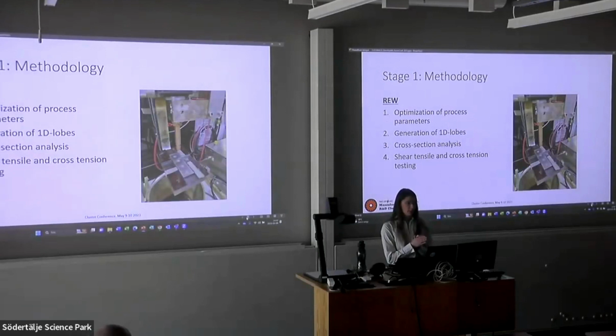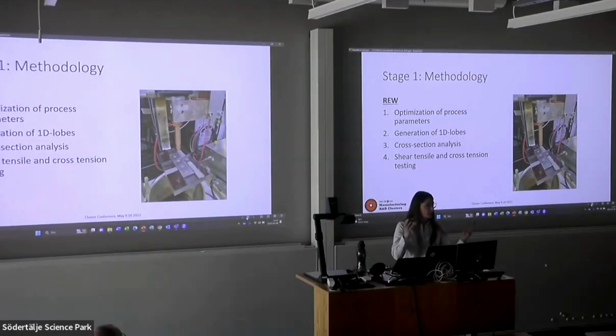First, for resistance element welding, we of course optimized the process for the material combination. Then generation of 1D lobes, which is basically, at the predetermined minimum nugget size, the number of current steps you can achieve before a spatter or expulsion occurs in the joining. So you get the current interval called the approved current interval. They were evaluated by cross-section analysis, which basically means that we measured the nugget size. And then, of course, shear tensile and cross-tension testing.